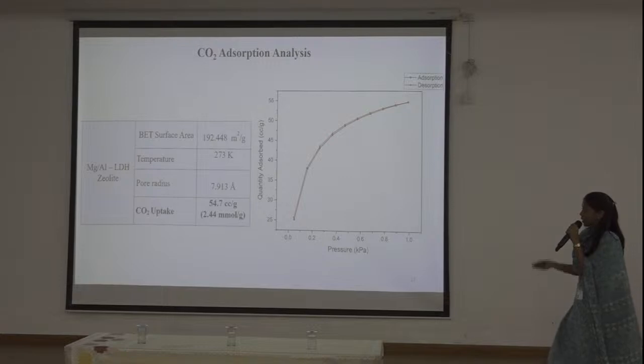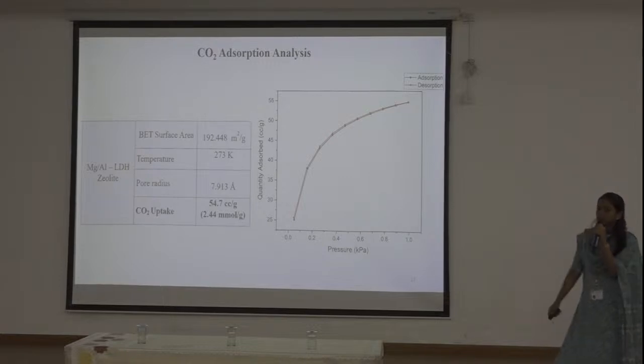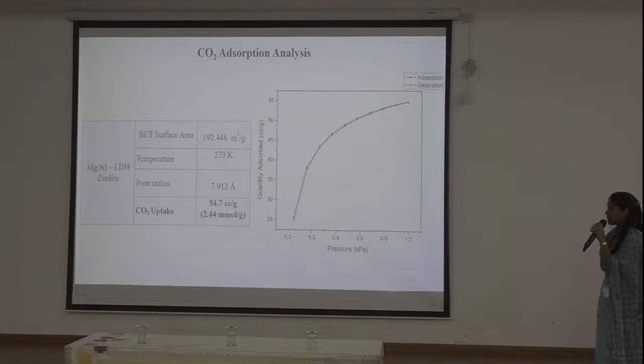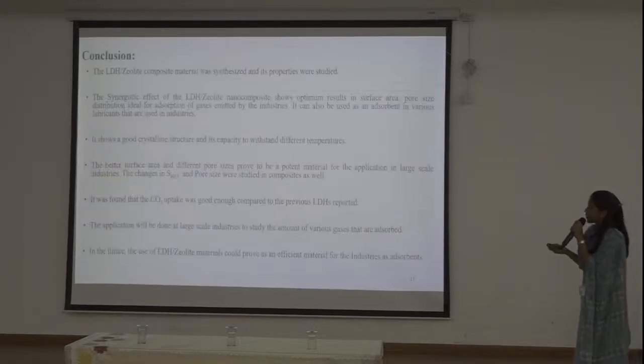For magnesium aluminum LDH zeolite, the maximum carbon dioxide uptake was found to be 54.7 cc per gram, which is 2.44 millimoles per gram.